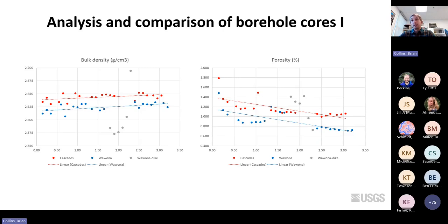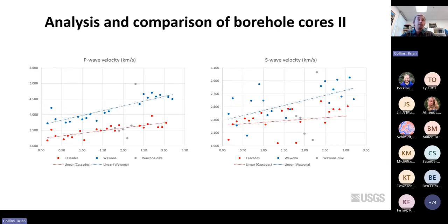In terms of porosity, I have to mention about the bulk density that we don't see any big changes in the bulk density with the depth. While when we look at the porosity, we can see a clear trend on both sides, where the porosity is decreasing with the depth. While when we measure the P and S wave velocities, we got actually nice results here.